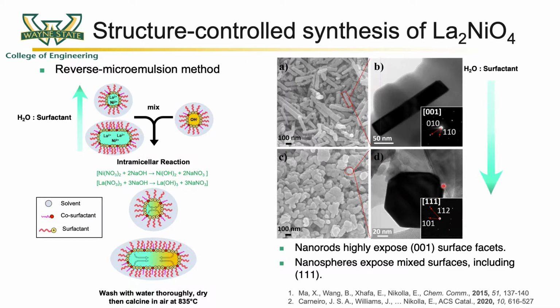Using transmission electron microscopy, we observe that the polyhedral shaped particles are terminated by multiple surface structures, while the rod shaped structures are terminated by single facets along the longitudinal axis.